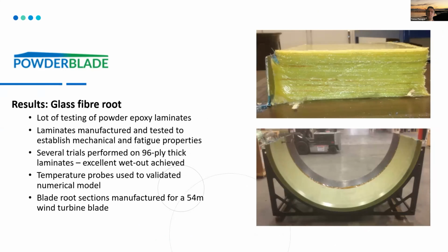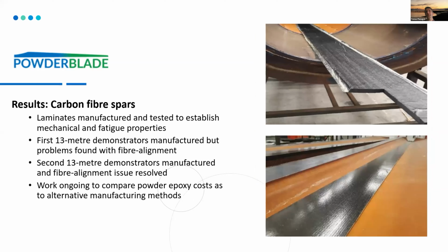So we made a glass fiber root section that was for a full-scale 54-meter blade. It was 96 plies thick, and we didn't have any problems with dry spots. We also used temperature probes within some of the smaller test panels in order to validate the computational model, and we got good correlation. Also, we made some carbon fiber spars, so we made these up to 13 meters long, and they're about 10 millimeters thick. And in the first efforts, we had issues with the alignment of the fibers, but we actually resolved that subsequently and got pretty good fiber alignment.